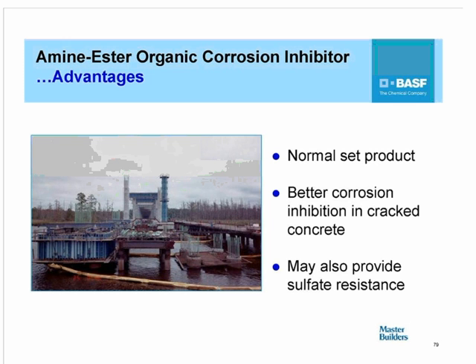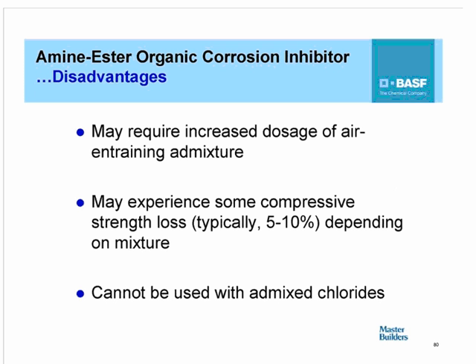The amine ester inhibitor is a normal set product, so it doesn't affect the time of set of the concrete, and it works by means of a twofold mechanism, which is one, reducing the permeability of the concrete, and also providing an increase in the chloride threshold at the surface of the steel. Now, because of the reduction in permeability that you get with this material, it also provides a modest increase in sulfate resistance when used in concrete.